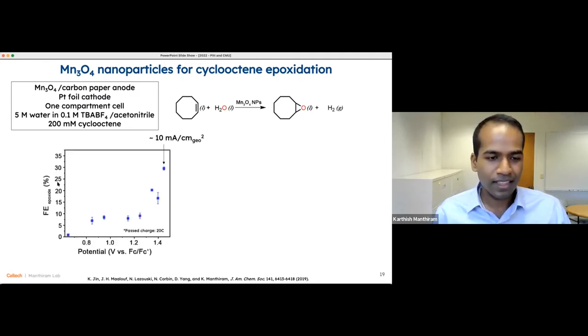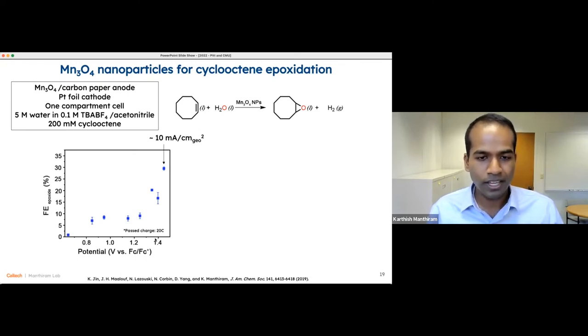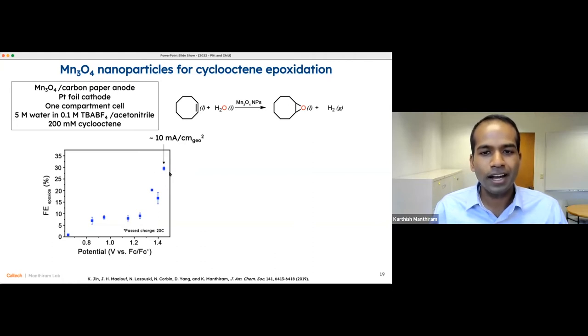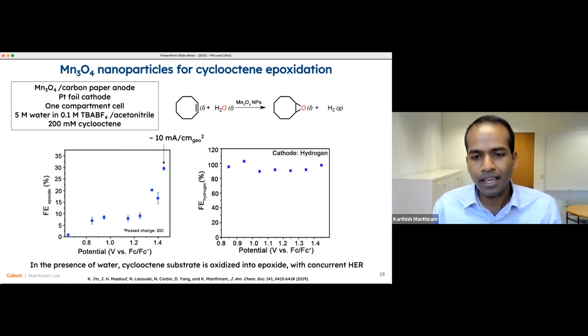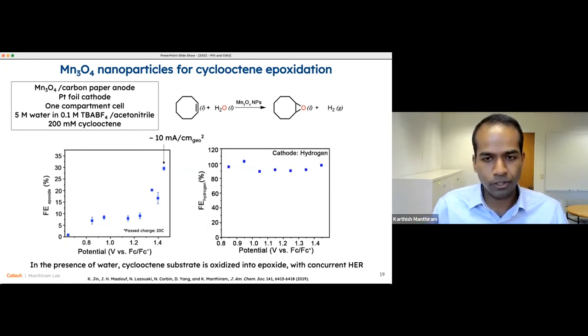And we find that the Faraday efficiency for epoxide, as we go to more oxidizing potentials, we could actually get up to about a third of the electrons to go to the right place. So we were pretty excited to see that this reaction was in fact possible over manganese oxide. At the cathode, we're making hydrogen pretty selectively, so about 100% Faraday efficiency averaged over time. And that, of course, is an unoptimized electrode on the other side of this reactor.